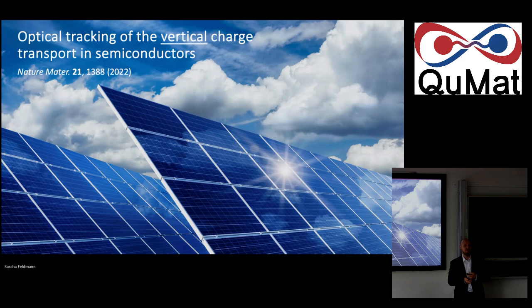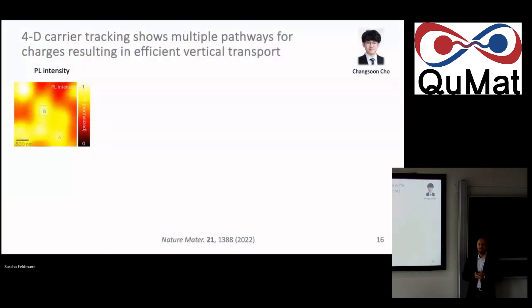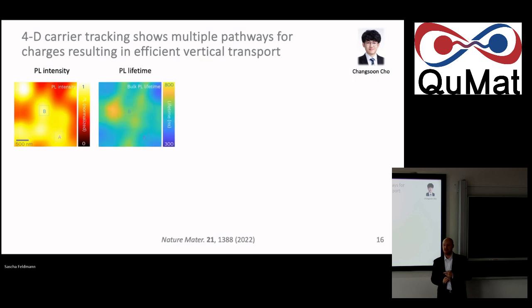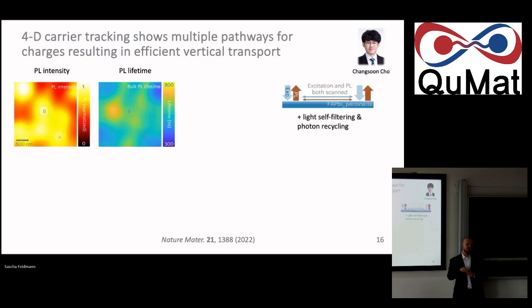Now, how does that work, you might ask? Well, first, we need a thin film material, but there are quite a few. We need to get some light through and out. This is really work led by Chang Soon, who was a master's student here and is by now also an assistant professor in Korea. Fantastic guy. So we start again with our photoluminescence map. This time I plot the PL intensity, not the energy. And pixel for pixel, we look now at the luminescence lifetime, which, just like the intensity, is quite heterogeneous yet again from all this disorder and all these defects. So the PL lifetime also varies on this micron scale or so. What we now also didn't do before is we don't just excite locally with our confocal microscope and detect locally, but also away from the excitation center quite a bit.